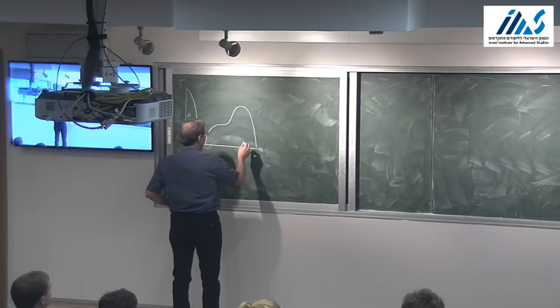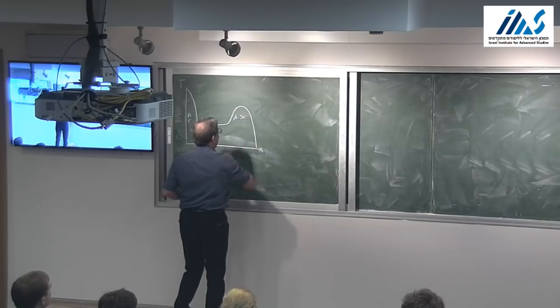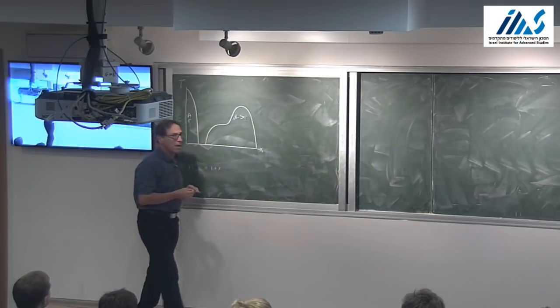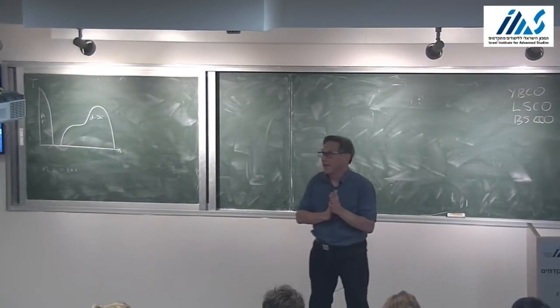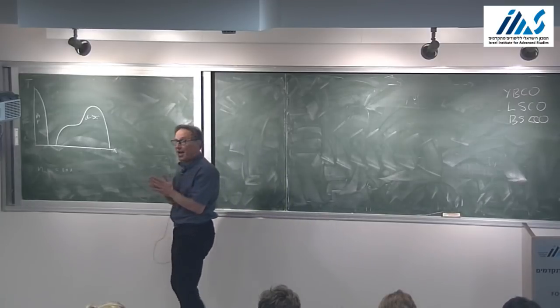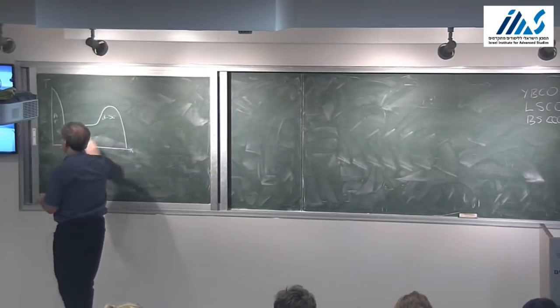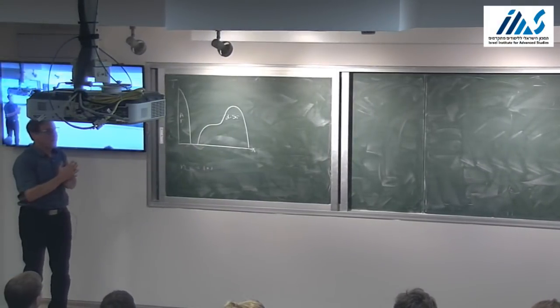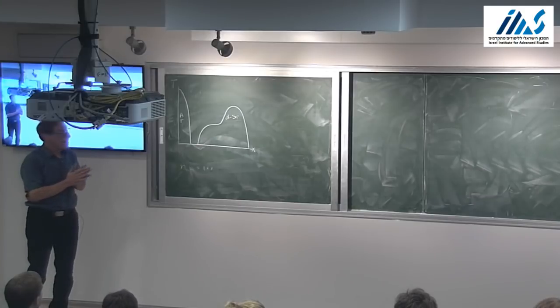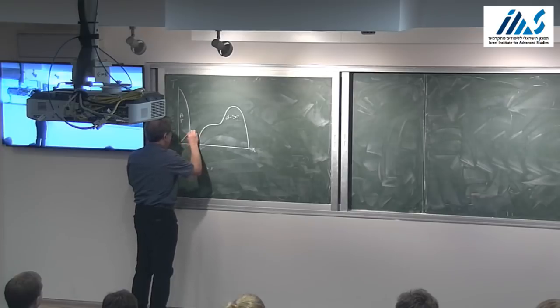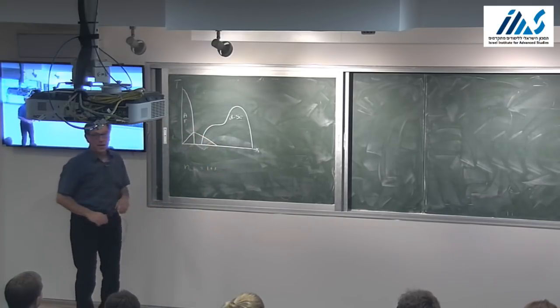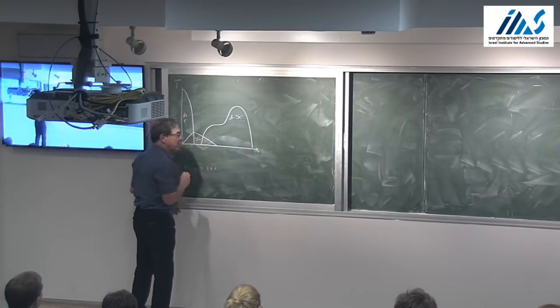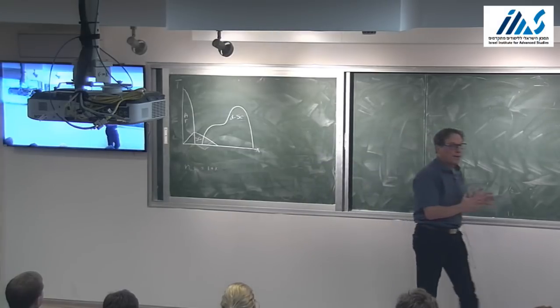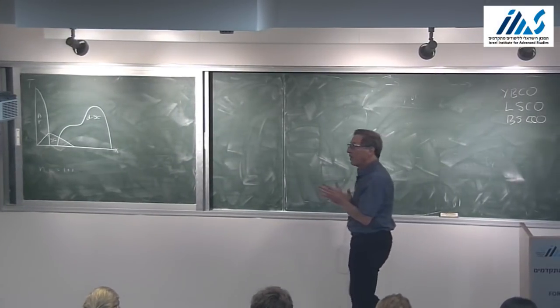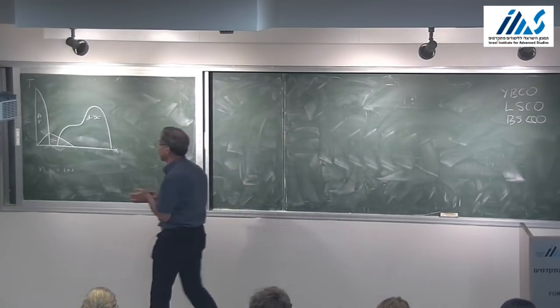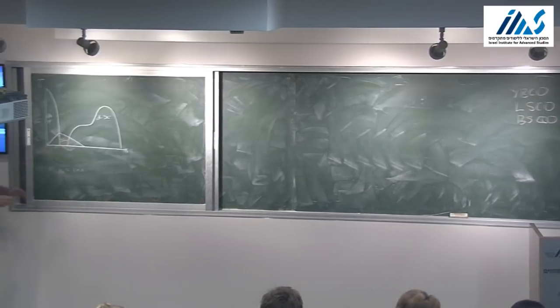Okay, so this is a superconducting phase, and it's in fact a D-wave superconducting phase, and this is a phase transition, and so although details of the shape may matter from material to material, again, this part of the phase diagram doesn't need a lot of caveats associated with it. There are a few other lines I want to draw. There's a line that goes something like this, and this is a spin glass transition. And, well, probably that's a real transition. Spin glasses are a little bit complicated in any case, but this is as good as any other spin glass. There's some spin freezing that occurs here.